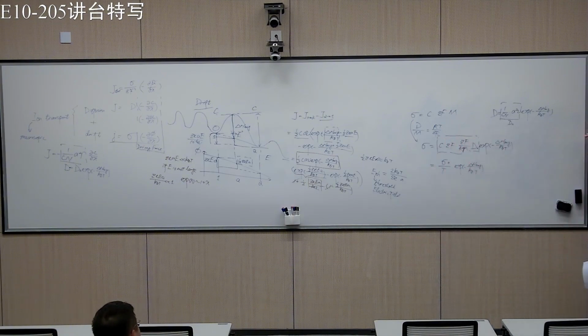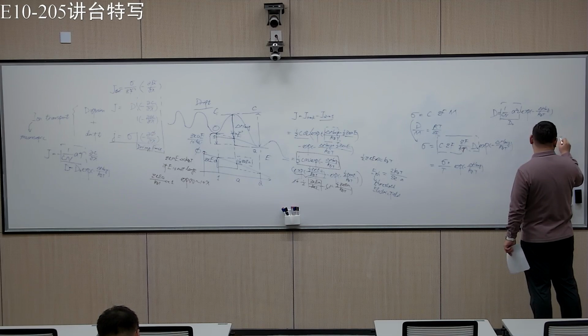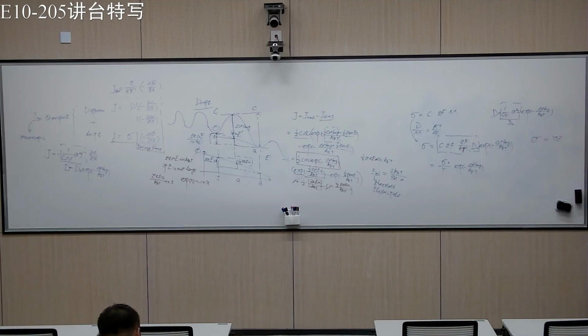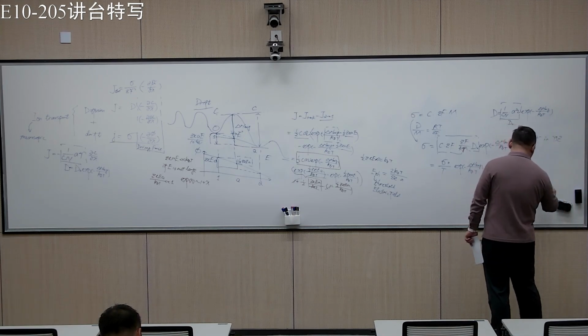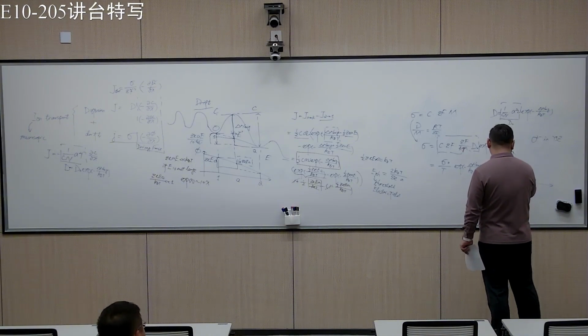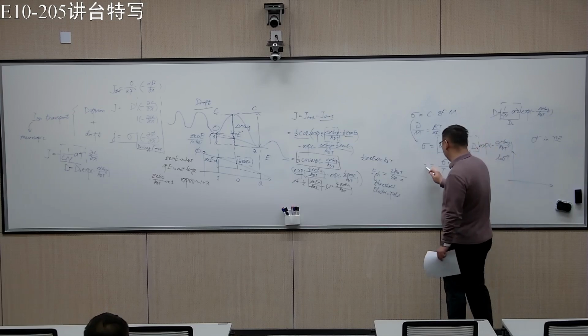Okay, so if you have some ionic species, for example, if you think about the oxygen vacancy or oxygen ions in YSZ, or lithium ion transport, what you should really plot is basically log sigma T. If I put a T here, so this is sigma.